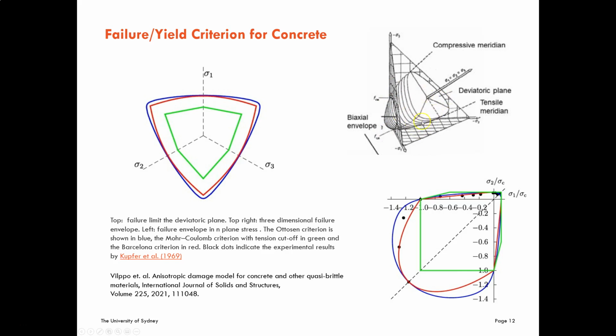So if we do a cut in the deviatoric plane, we obtain that this is the Mohr-Coulomb criteria, and it's different from the more advanced models that represent the real data. Like here is represented the Ottosen criterion or the Barcelona criterion. The major difference you can see in the plane stress analysis when we assume that one of the components is 0. So it's going to be the intersection of this surface with a plane. So these intersections are represented here. So this is the failure envelope for plane stress analysis.